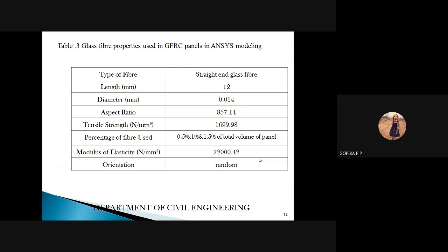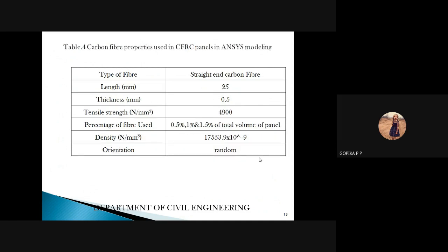Then this table shows the glass fiber properties used in ANSYS modeling. Type of fiber, straightened glass fiber, length 12 mm, diameter 0.014 mm, aspect ratio 857.14, tensile strength 1699.98, percentage of fibers used 0.5, 1% and 1.5% of total volume of panel, orientation random. Then this table shows carbon fiber properties used in ANSYS modeling. Type of fiber, straightened carbon fiber, length 25 mm, thickness 0.5 mm, tensile strength 4900 Newton per mm square, percentage of fiber used 0.5, 1 and 1.5% of total volume of panel, orientation random.